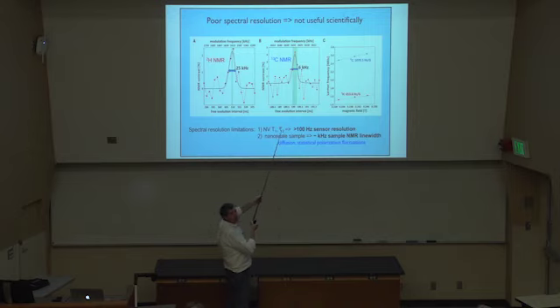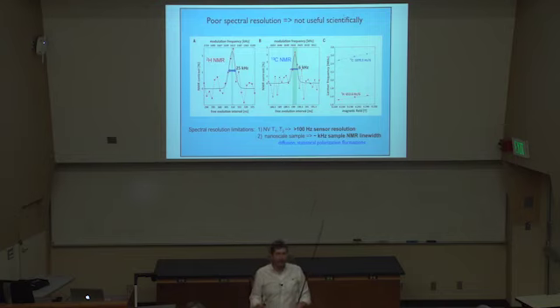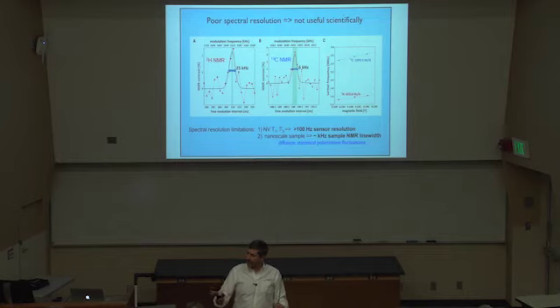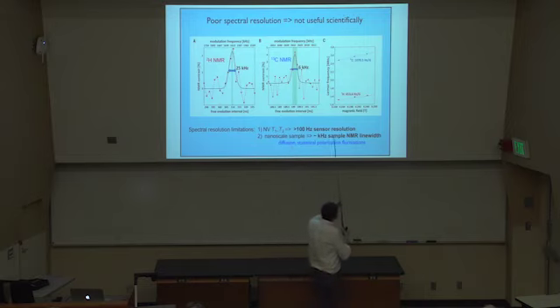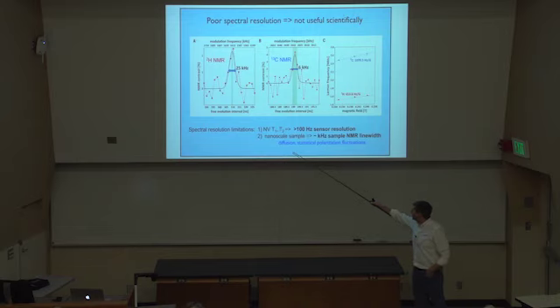Even with the best fancy correlation measurement techniques, you're limited to about 100 hertz spectral resolution due to the sensor. So the NV sensor itself could only see things down to 100 hertz at best. You might think that sounds good, but hold on. The sample is a nanoscale sample, a single protein, so it has a very large, kilohertz sample line width due to a variety of phenomena.